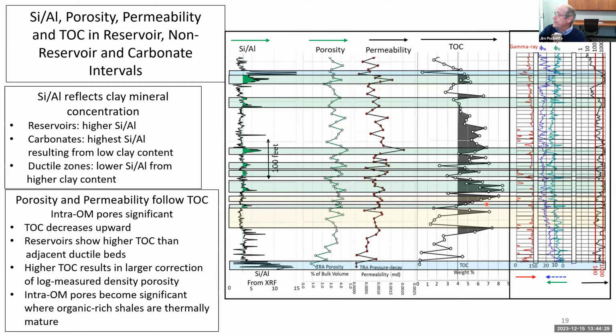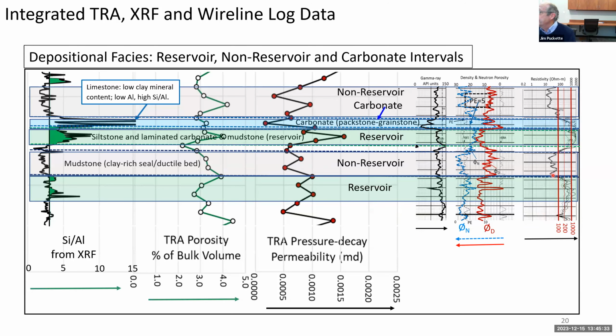So how important is organic matter? Well, it looks like it may be as important in the Caney as it is in some areas in the Woodford, where a significant amount of that porosity and storage capacity in the Woodford, and now maybe so in the Caney, may be in organic matter, and it's something that needs to be looked at in more detail. And down at the bottom here, fortunately, I have a carbonate interval that has very low porosity, very low permeability, and low TOC. We see some patterns that develop in using core calibrated logs that I think when we step away from core, if we see some of these wireline log characteristics, they're telling us some ways that we can identify reservoir and non-reservoir intervals.